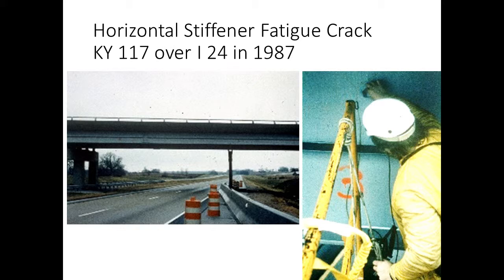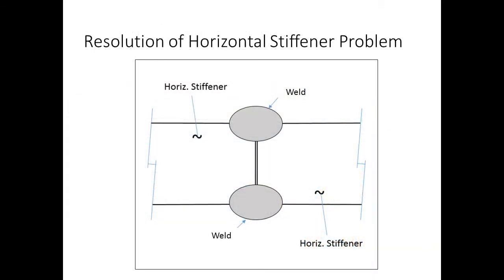But after this was done, the cabinet had a lot of concern because this horizontal stiffener detail was pretty common on deck girder bridges. So they did some studying and determined that the problem occurred in the fabrication shop. To form a sufficiently long stiffener, they would take two pieces of bar stock, butt them up together, and then put a weld on the top and a weld on the bottom, and then they'd weld those to the web of the girder, and then the girder would be put in service, and then problems ensued.